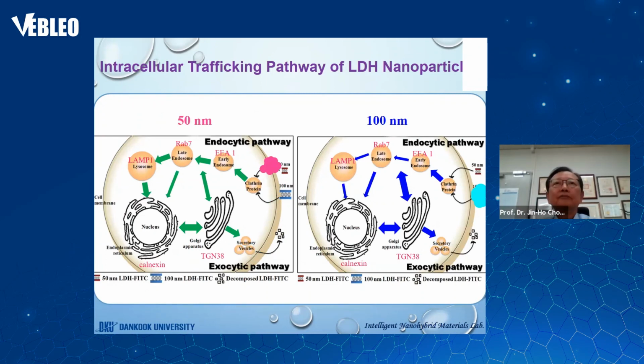Well, as I already mentioned, the 50 nanometer particles select two different pathways with the same degree, such as the typical endocytic pathway represented by the early endosome, late endosome, lysosome, and the exocytic pathway represented by the early endosome, Golgi. In case of 100 nanometer particles in the right-hand side, the direct exocytosis pathway represented by the early endosome, Golgi is clear, rather than escaping from typical endosomal lysosomal degradation. It is therefore concluded that LDH nanoparticles with a size of 100 nanometer may have a great potential as a delivery nanovehicle for gene delivery due to their unique size dependent intracellular trafficking pathway with the endosomal and the lysosomal escapes.